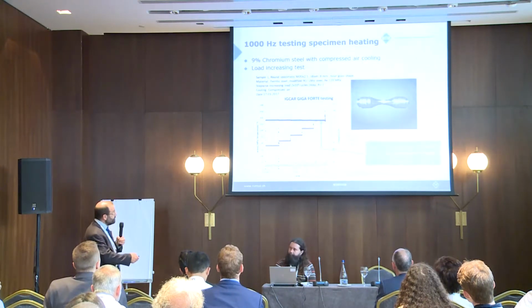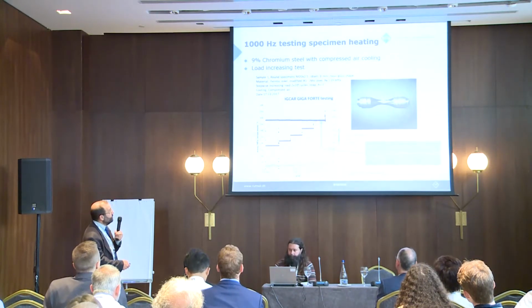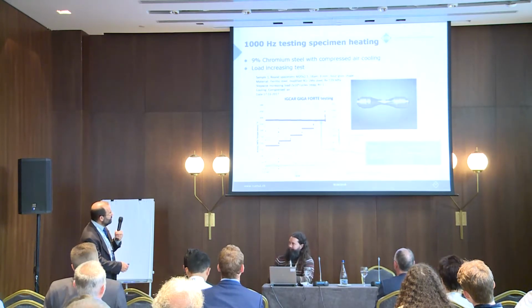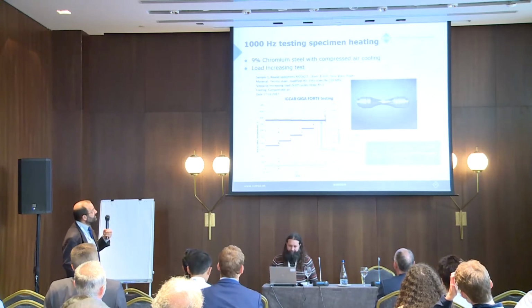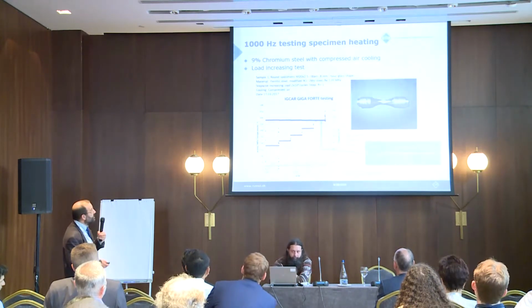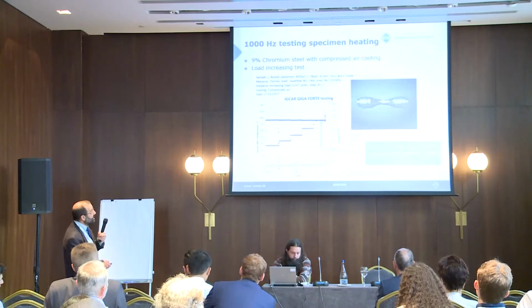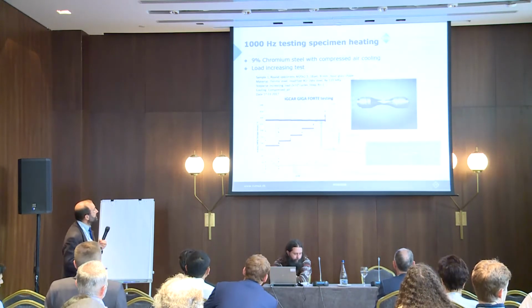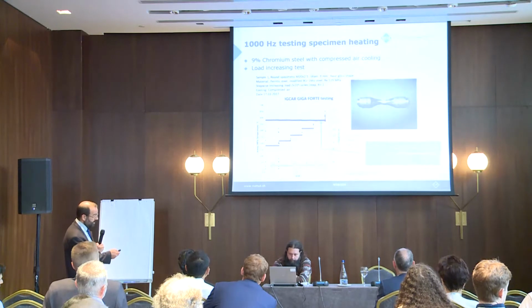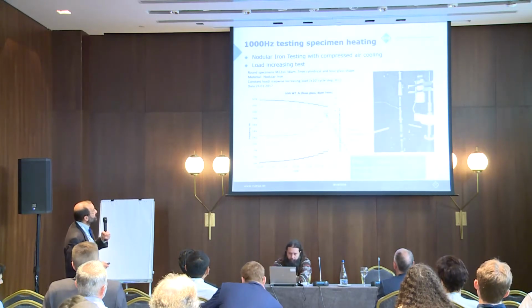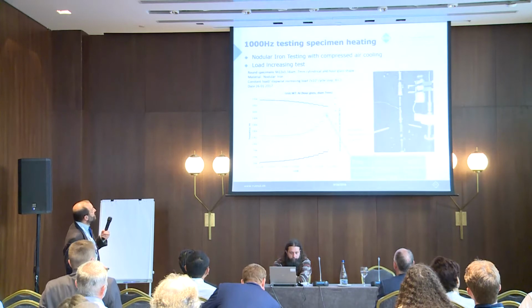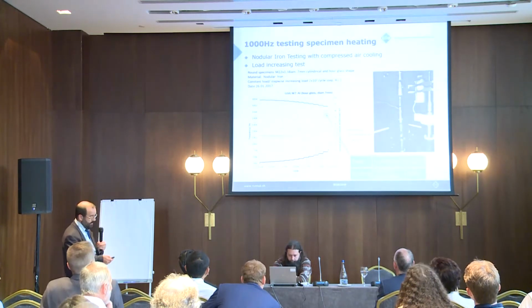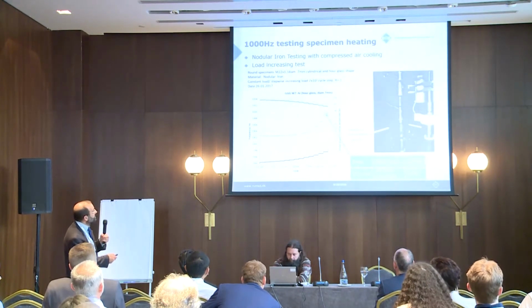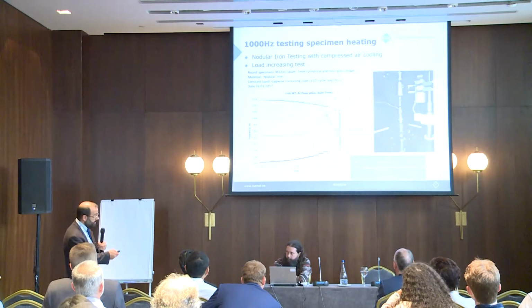So at this test run with 1024 hertz, at a load then of 333 megapascal, the temperature was 26, respectively 54 degrees without any cooling. So the cooling is very efficient. Another example with a higher damping material, here the test run only with compressed air, nodular iron. The behavior is similar as expected.